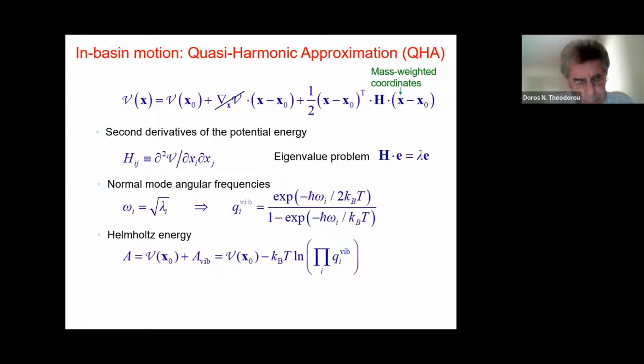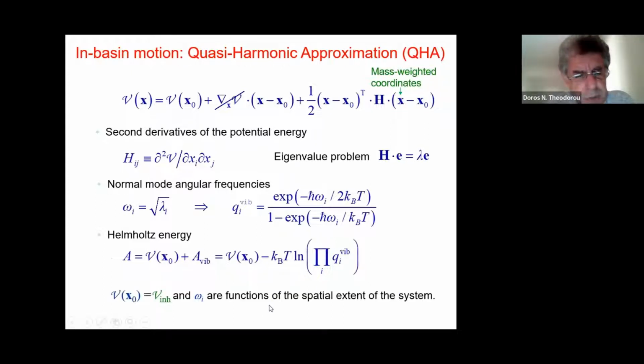It is important to realize that the inherent structure energy and the eigenfrequencies are functions of the spatial extent of the system. If we change the dimensions of the system, both the inherent structure energy and the omegas, the frequencies, change. So essentially, this here is a fundamental equation of thermodynamics for the arrested material that gives us the free energy as a function of temperature and the spatial extent. And we can use it as a starting point for getting thermodynamic properties for the glass.